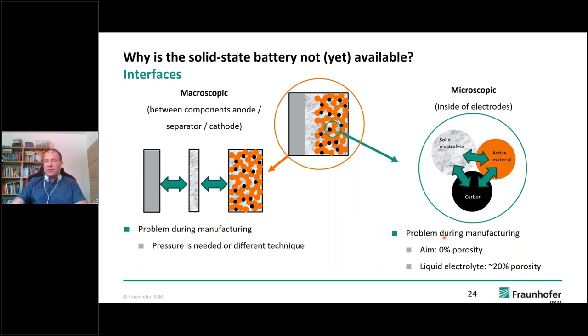So during manufacturing, we actually don't want any porosity. This is different for liquid electrolytes, because when we make cathodes for liquid electrolytes, we want porosity, because the liquid electrolyte is filled in afterwards and has to flood the whole cathode.